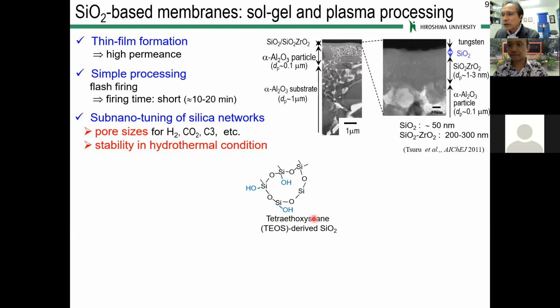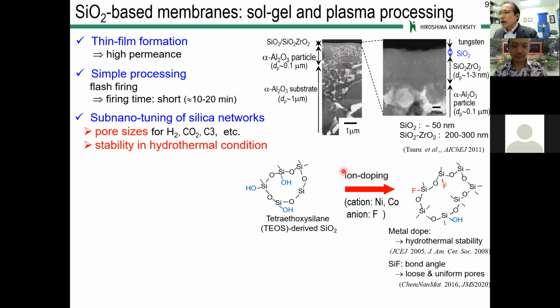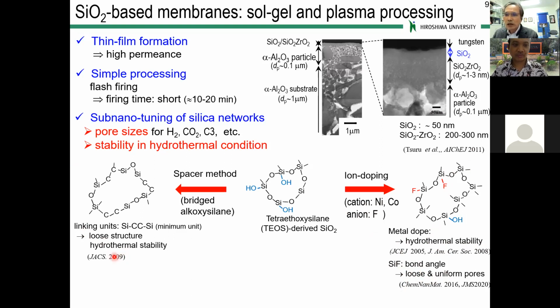This typical network is prepared from tetraethoxysilane, TEOS-derived silica networks. We reported ion doping. Since this silica network is flexible, we doped it with metal ions such as nickel or cobalt to increase the hydrothermal stability. Anions such as fluorine can be doped to make SiOF like this, to make the network loose and uniform. We reported in 2009 special techniques using bridged alkoxysilane.